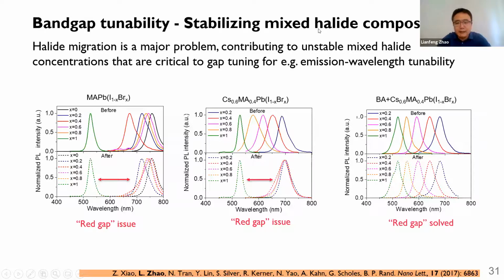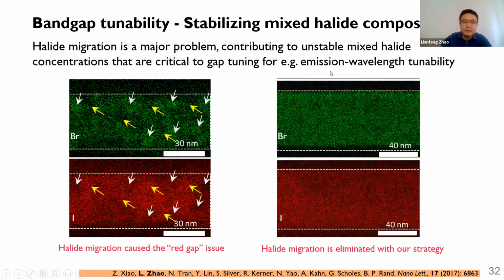Using our strategy of adding the bulky organoammonium additives, we were able to precisely tune the wavelengths, and it's very stable. We further studied the mechanism at the nanoscale. We found that for the control samples, the distribution of iodide and bromide is not uniform. For areas where the bromide concentration is high, the iodide concentration is low. And for areas where the bromide concentration is low, the iodide concentration is high. This halide migration caused the red gap issue. Using our strategy, these organic additives can prevent the halide migration, and you can see the distribution of bromide and iodide is very uniform.